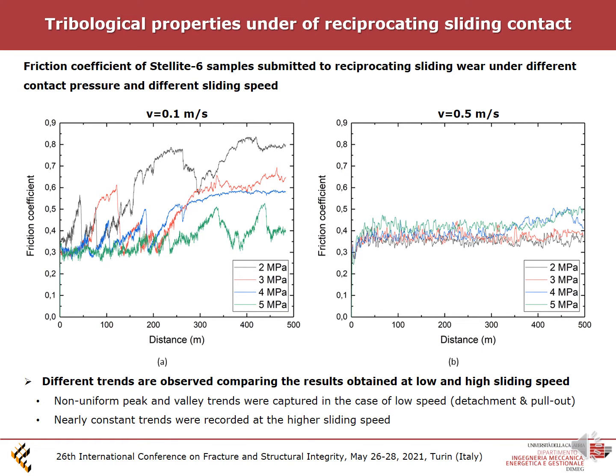In this slide, I reported the trends of the dynamic coefficient of friction obtained from reciprocating sliding wear experiments as a function of the sliding distance for the different values of the contact pressure and for the two investigated sliding speeds, 0.1 and 0.5 meter per second. And how you can see, a non-uniform peak and valley trend was captured in the case of low speed, in particular for the low values of the contact pressure 2 and 3 megapascal. On the contrary, nearly constant trends were recorded at the higher sliding speed, that is 0.5 meter per second.